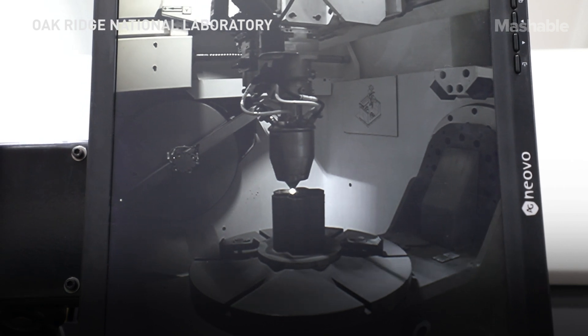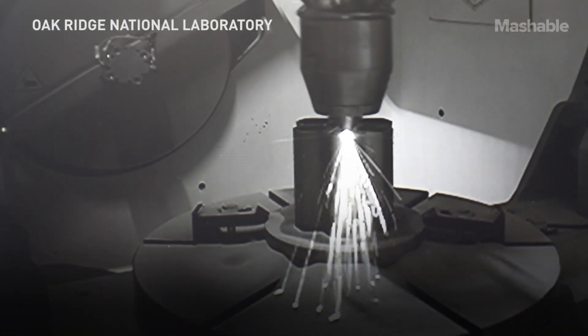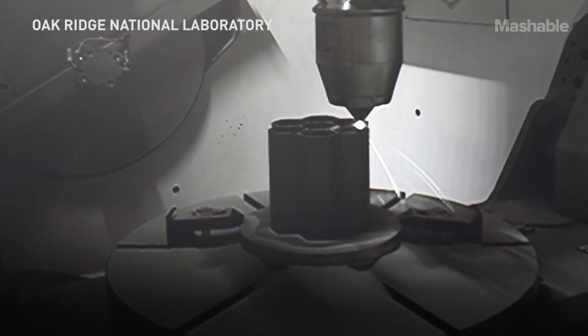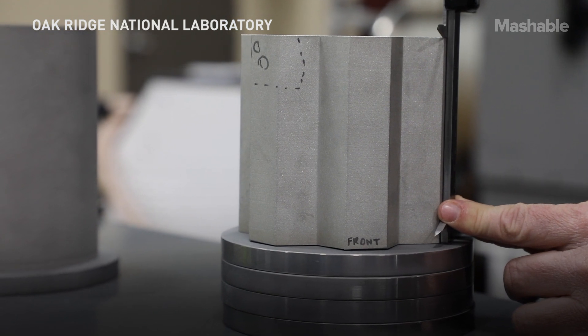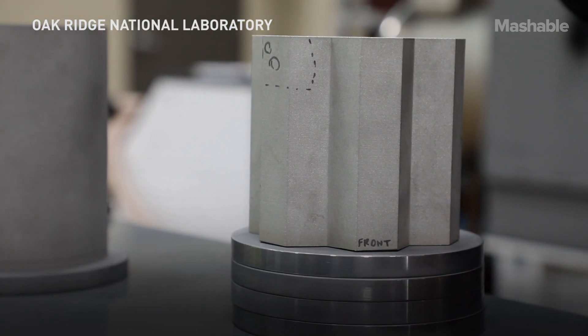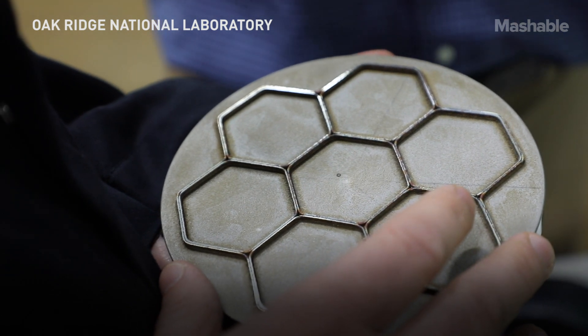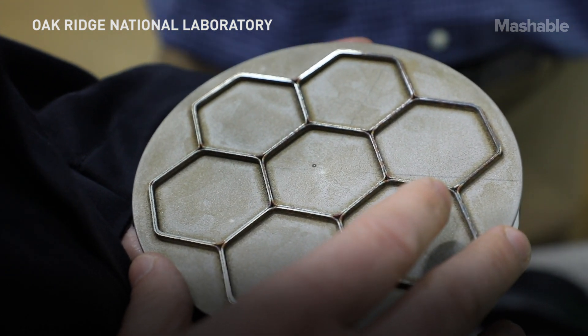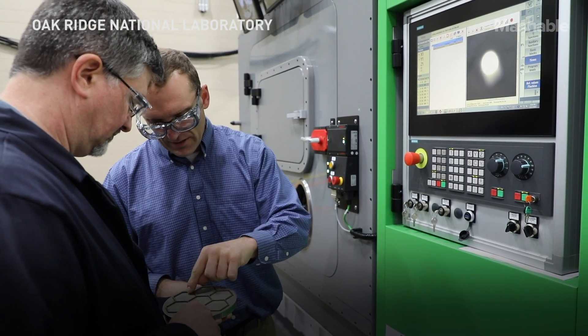It's in a refractory ceramic carbide matrix. It can go to very, very high temperatures and withstand very harsh environments. We take our fuel blocks and combine them with what we call a moderator, which you need to slow down the neutrons in a small core. For the moderator, we're using yttrium hydride — a brand new material that hasn't been used before. We combine the yttrium hydride and stainless steel structures and put our silicon carbide fuel blocks around it, and that forms our core.